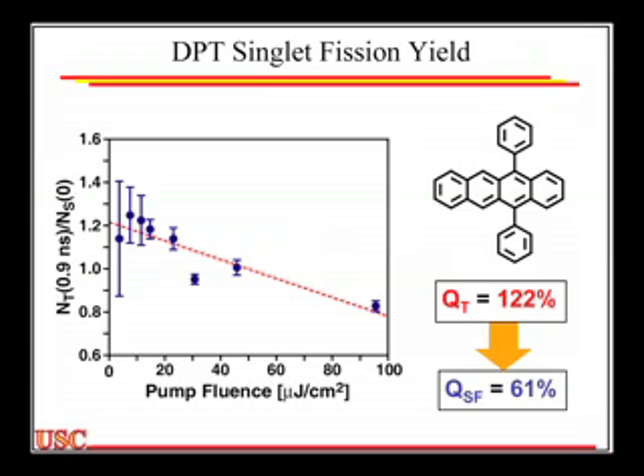So for every singlet that we generate, 1.2 triplets. So I'd like it to be 2, but I think it's pretty good that we're doing this in an amorphous film already, and I already know where the losses are. Right, the losses are in this diffusion delay. So if we can play some games to decrease the diffusion delay, we'll do even better than that.